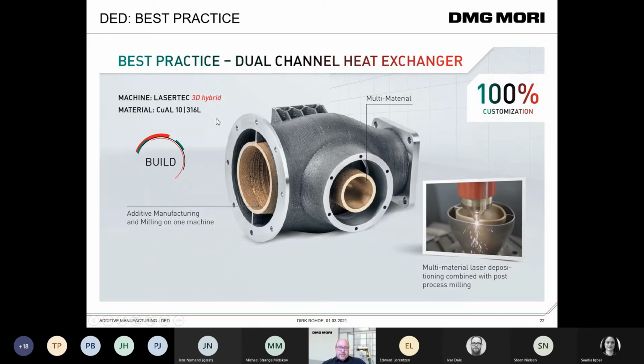This is a part we developed on our own, a tube in tube, but this is one of the best samples. DED technology is capable of handling in standard 2 different materials. Compared to the SLM, you have one big powder bed where your powder is in, you cannot mix the powder. But here, you can imagine that we blow the powder to the nozzle, and due to this blowing process, we can make a clean shot and then switch the valve and feed a second powder to the nozzle. So here you have a mix of stainless steel and bronze in the middle. It's a great combination, and right now we are able to make a mix up to 4 different materials.